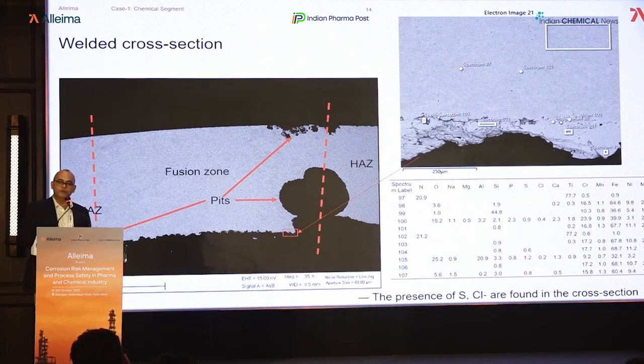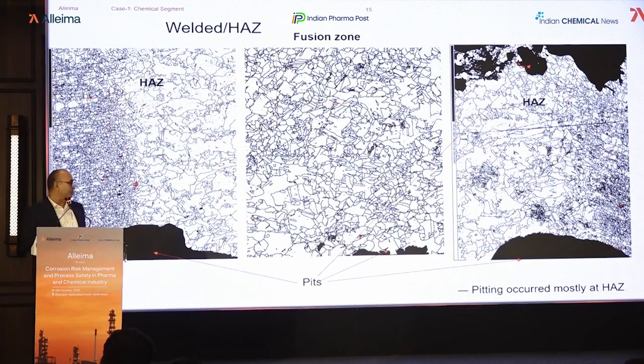Whenever you do welding, you have the fusion zone. Next to that, you have the heat affected zone, which is at a lower temperature. And if you have stainless steel, that has its own challenge. We'll talk about that. We could see that most of the pitting occurred in the heat affected zone. But of course, here we can see that it was also in the fusion zone. Let's look into the microstructure in the heat affected zone and fusion zone.